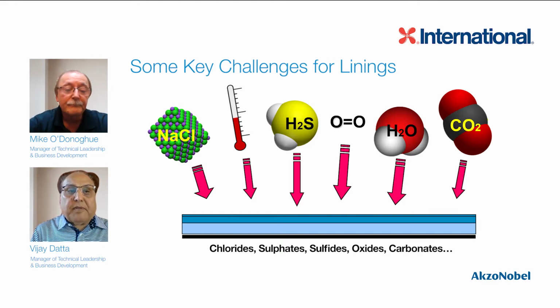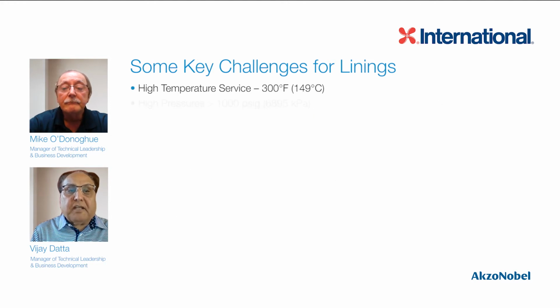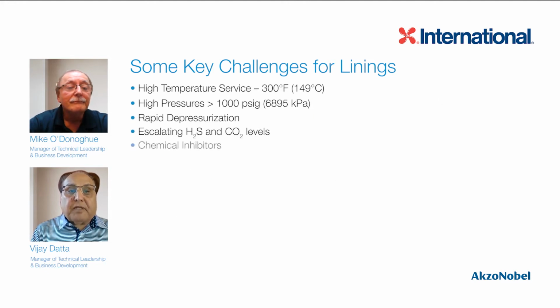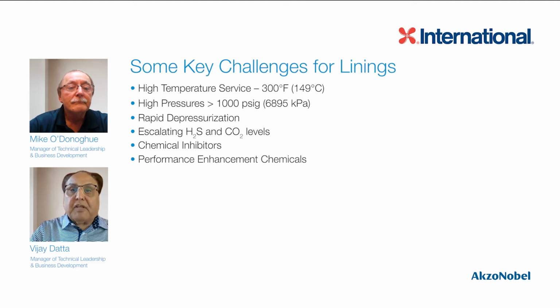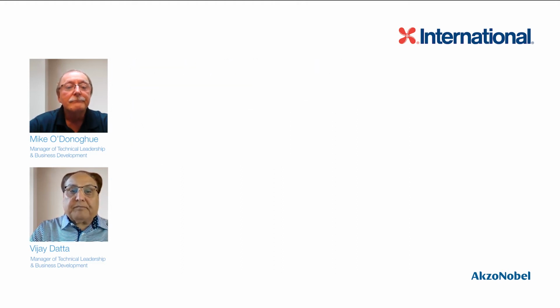That's right, Mike. And in addition, there are additional challenges for the linings here. Like you mentioned, very high temperatures. Yes, when the crude oil is very heavy, we need very high temperature processing facilities, more than 300, 350 degrees F. High pressure, more than even 1,000 PSI. Rapid depressurization can really cause a lot of problems for the coating. And there are very high levels of hydrogen sulfide and carbon dioxide. Chemical inhibitors, and a lot of people are putting in different performance enhancement chemicals which can really affect your coating. And with that in mind, we need to have an epoxy that can handle all of these different factors.